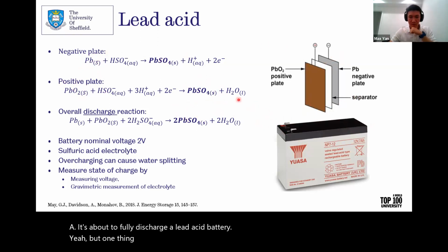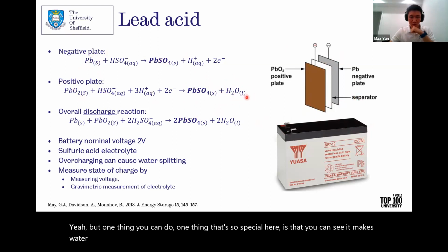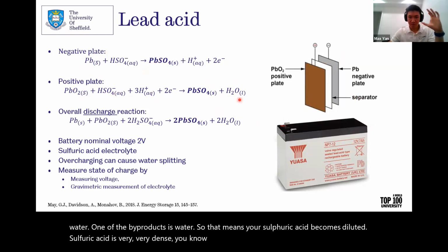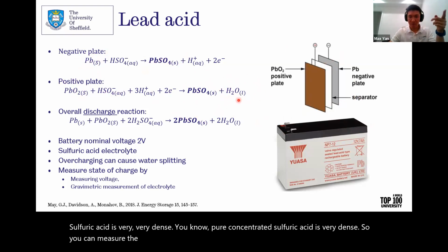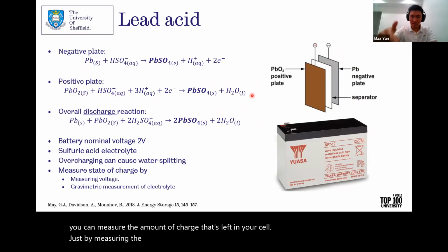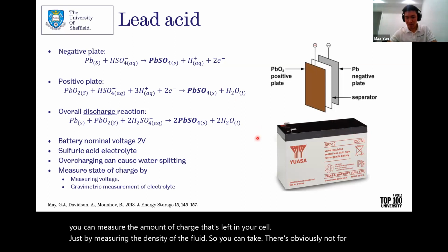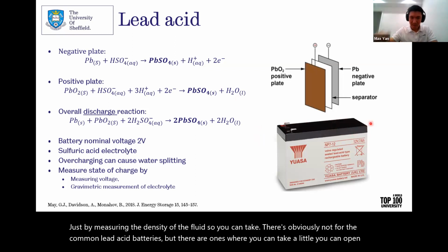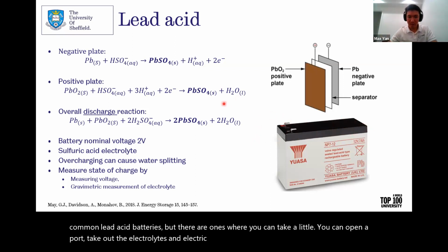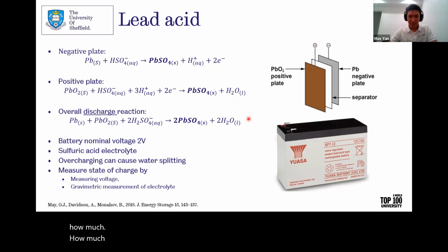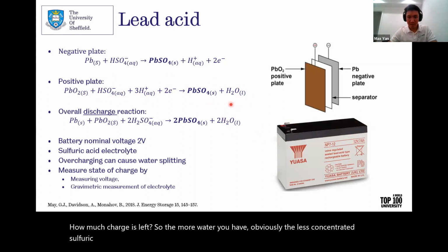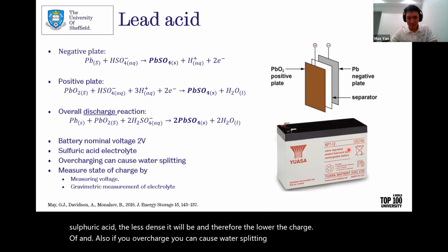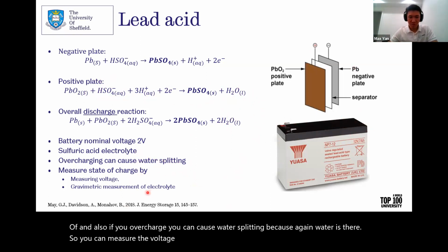But one thing that's so special here is that it makes water. One of the byproducts is water. So that means your sulfuric acid becomes diluted. Pure concentrated sulfuric acid is very dense. So you can measure the amount of charge that's left in your cell just by measuring the density of the fluid. This is not for the common lead acid batteries, but there are ones where you can open a port, take out the electrolyte, and measure the density of it, and that tells you how much charge is left. So the more water you have, the less concentrated the sulfuric acid, the less dense it will be, and therefore the lower the charge. And also if you overcharge, you can cause water splitting, because again, water is there.